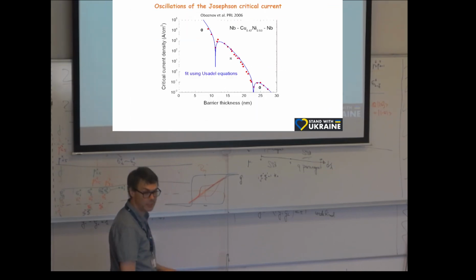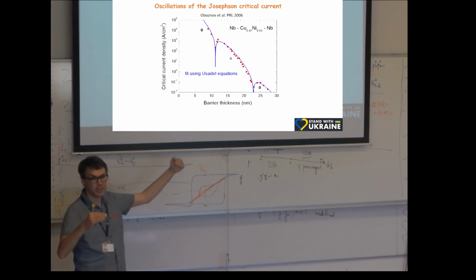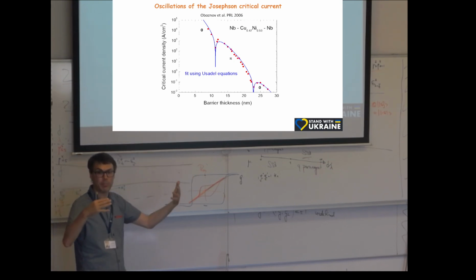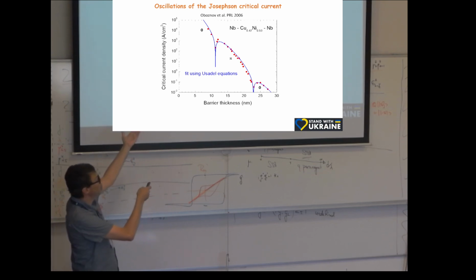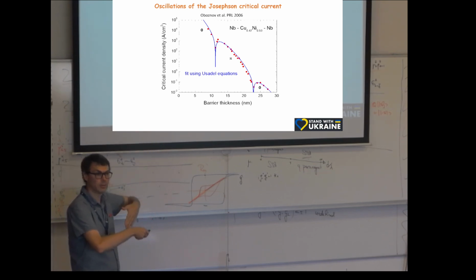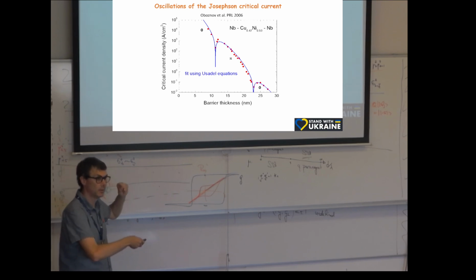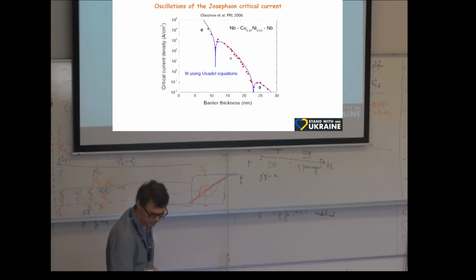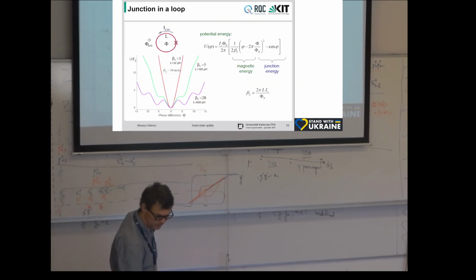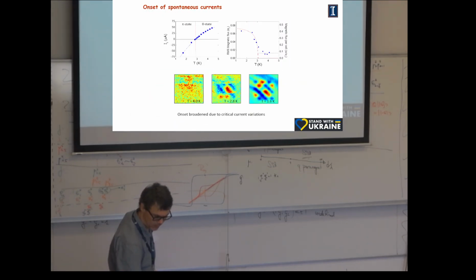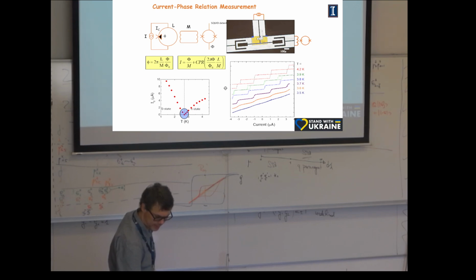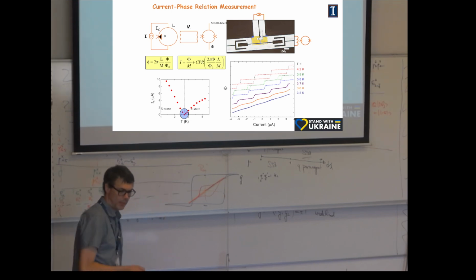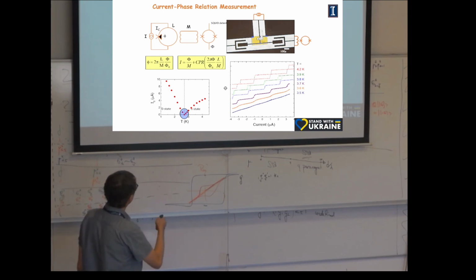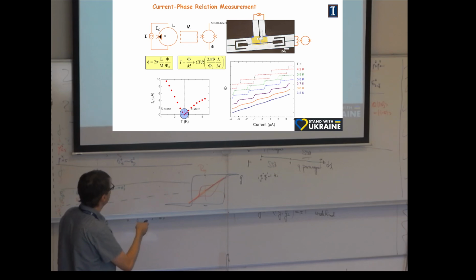So, for instance, in this measurement, what they were doing is just sending current through the junction and measuring the amplitude. So they could not tell which way it goes, where it flips. Right? But we could. Okay. So this is very nice. And another measurement we did, here actually the pi state was the high temperature phase and the zero state was the low temperature phase.